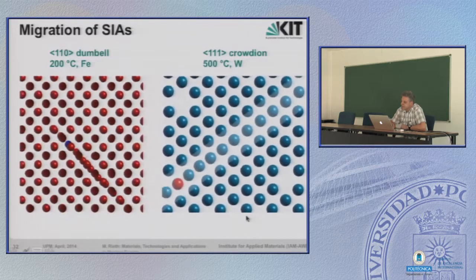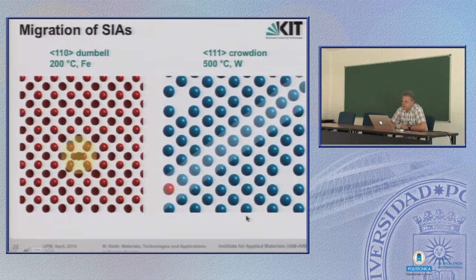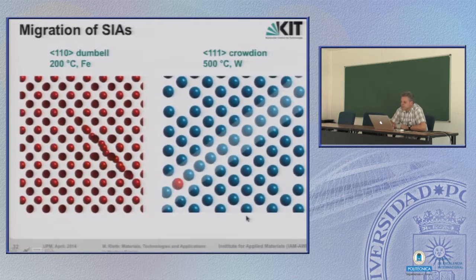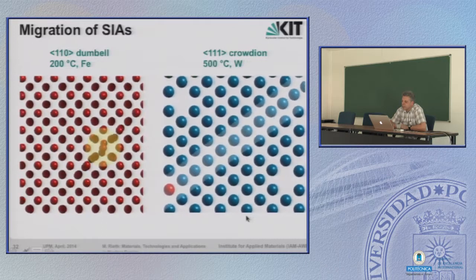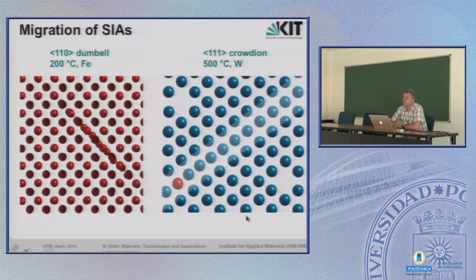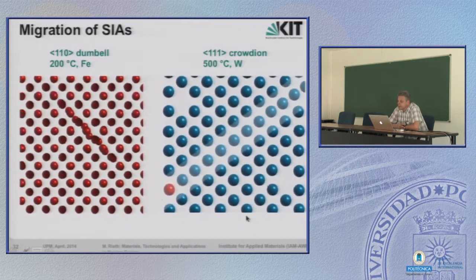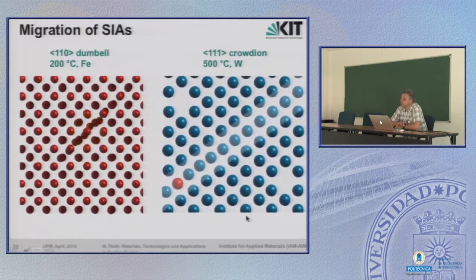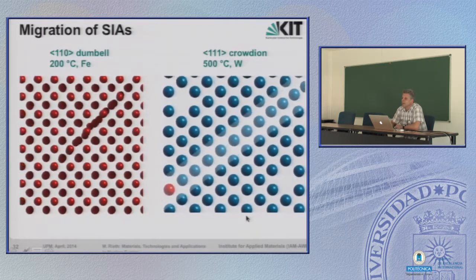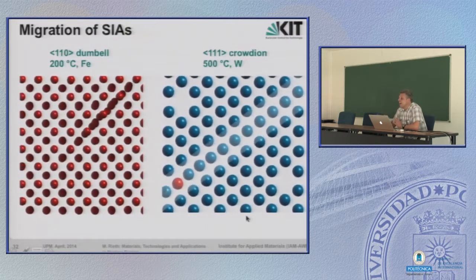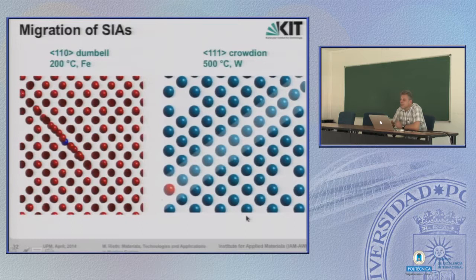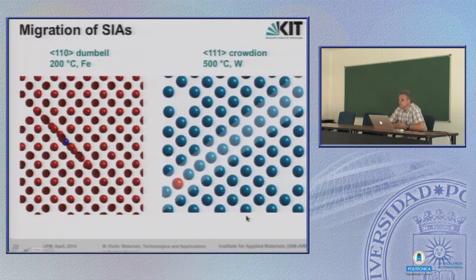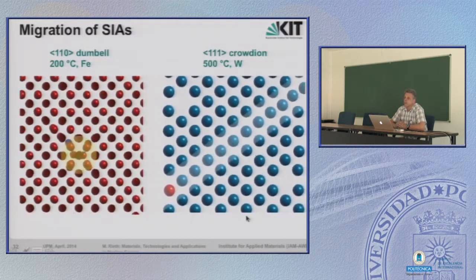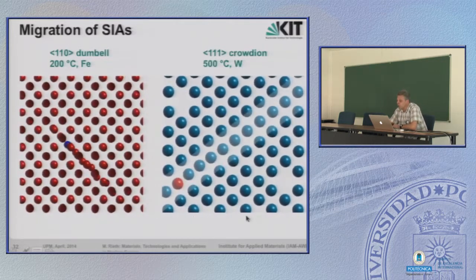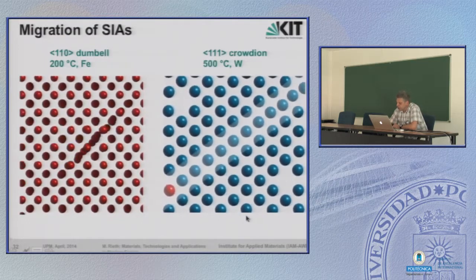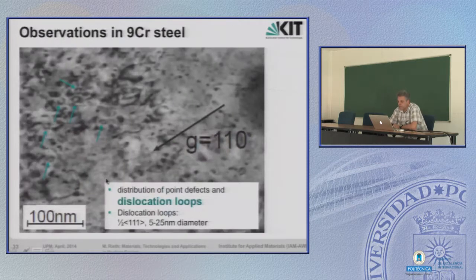It's simply squeezed through this 1-1-1 channel, whereas the dumbbell sometimes appears, then reappears, diffuses away, and then again you see it here, and so on. So there are several mechanisms and ways for migration of the self-interstitial atoms. So in general, the lattice is not a dead system, it's a living system. There is a lot going on, even at room temperature or slightly medium temperatures. A lot of these defects are moving around or migrating. Of course, there are also defects which don't, but most of them do.